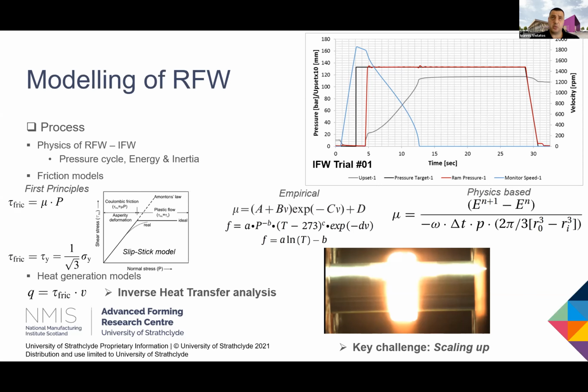What we have done in the past is that we have tried to use the inverse heat transfer tools available from software like Deform and Forge, and back calculate what the heat flux is, if we have a temperature measurement at specific locations in the material. And we found that, at least based on our modeling, we can get pretty close, and that will help us improve what we are doing with the heat generation.